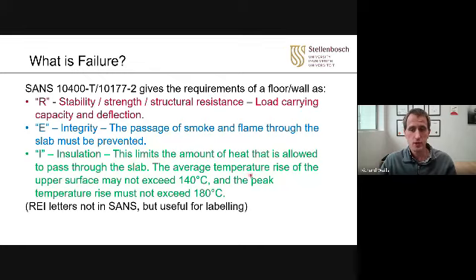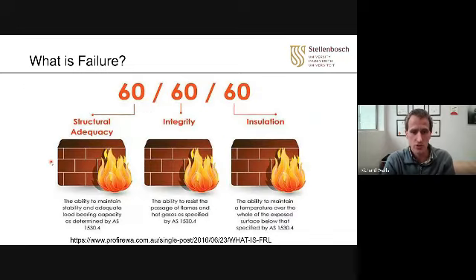The average temperature rise of the upper surface may not exceed 140 degrees Celsius, and the peak temperature must not exceed a set limit. So you have these requirements. And if you want a wall to pass a fire test, you need to satisfy all these criteria. Is it strong enough? Can smoke and flame pass through? Can it prevent heat from passing through as well? So if you had a really, really thin steel sheet, it heats up so fast that something on the unexposed side can ignite, boom, and so you'd need to check for this.